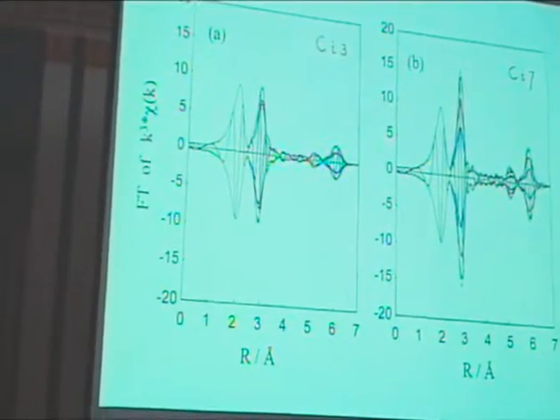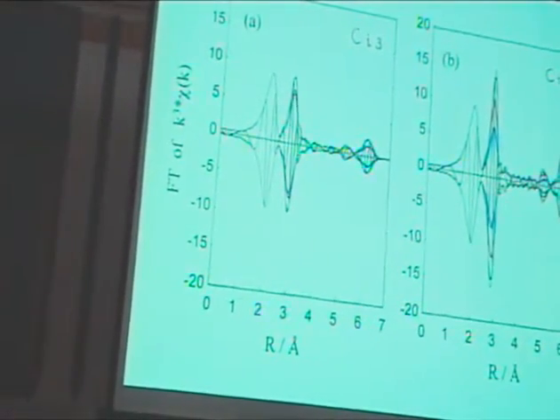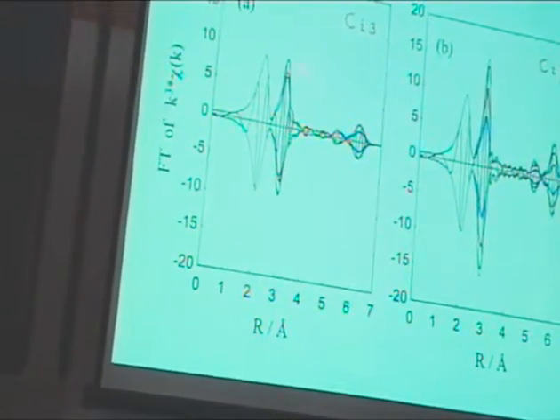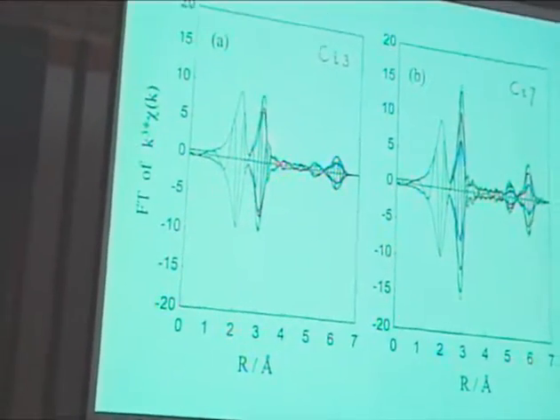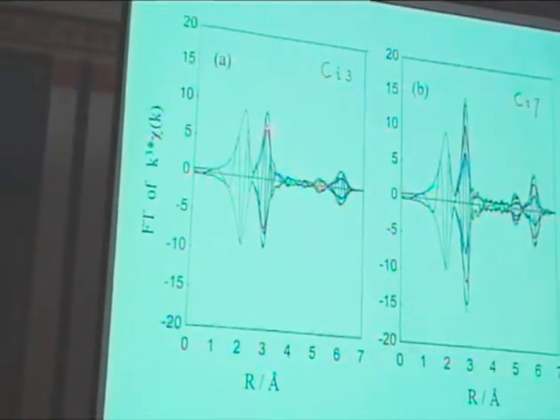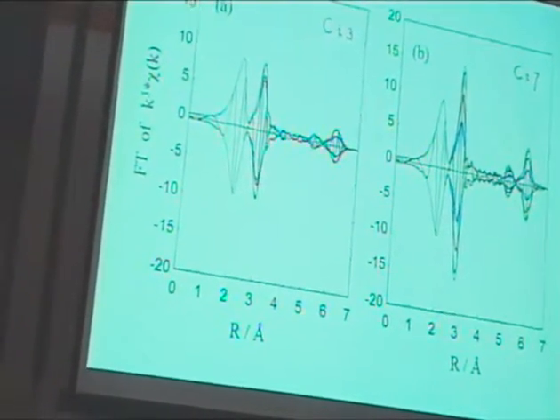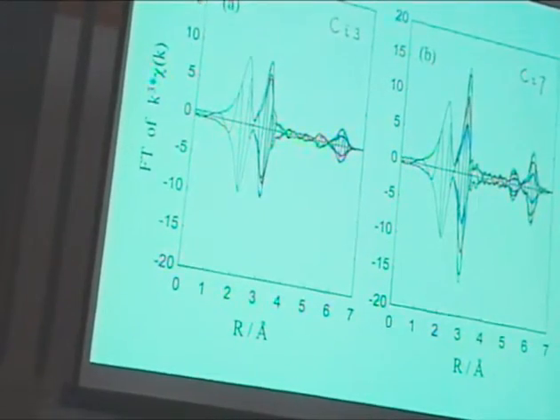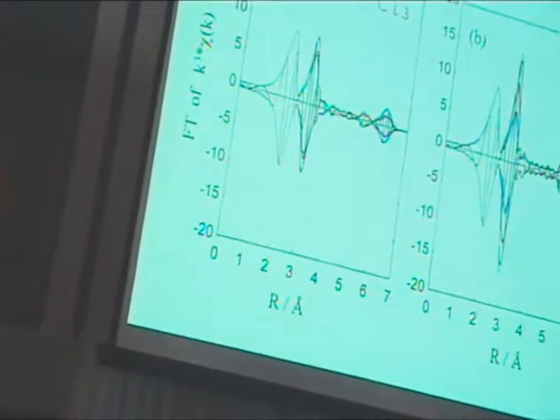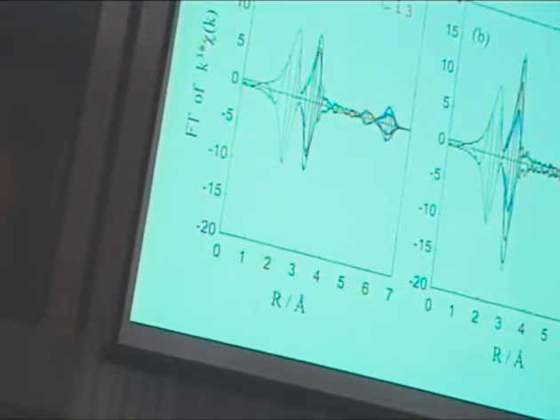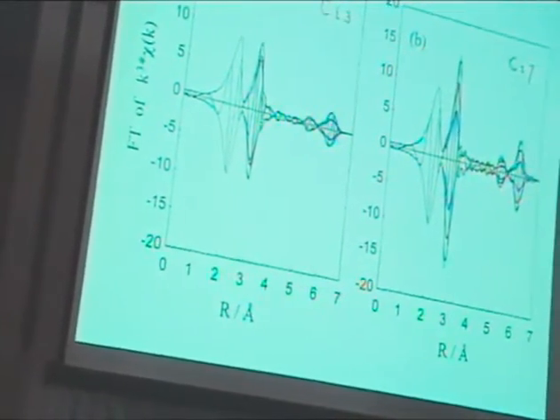So the third model, where we had a contraction as well as an elongation, but they were mild, works well. You don't see extra peaks in the analysis. You do see now that the second peak goes down, and the analysis now comes up with a coordination number which is 4, which is what we found in the original analysis. But it's only apparent. It's because of this distortion, and because of the randomization of the molybdenum position, that you get this apparent coordination number. And this led us to the following model.